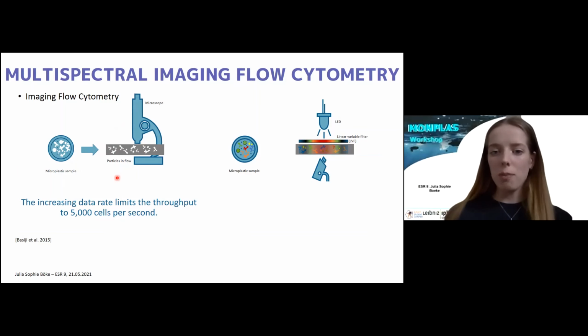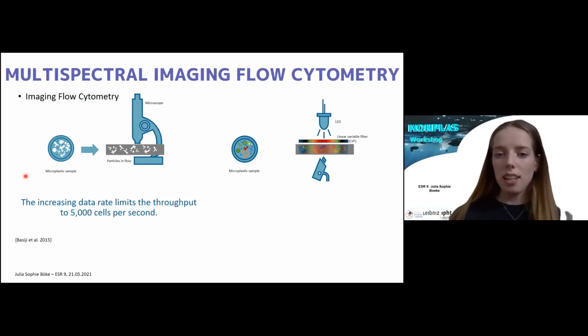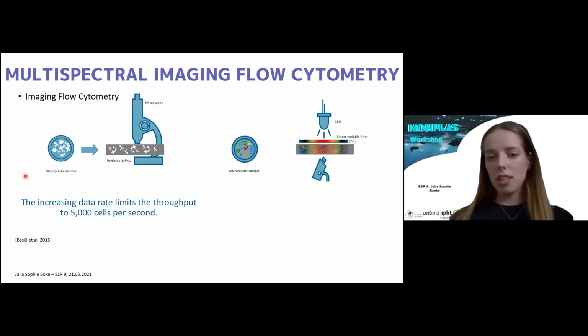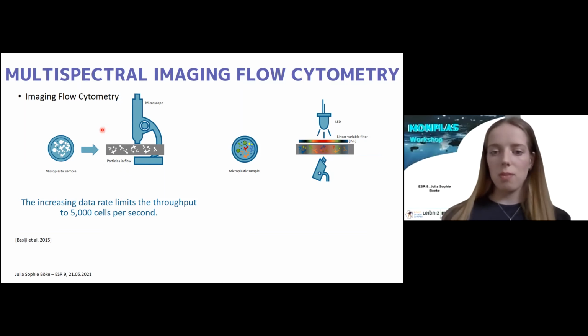So it's a very reliable technique with high throughput to analyze cells. You're able to assess the size from the scattering and partially their shape, but only partially. The main limitation is that you basically don't gain any additional morphological information or any information on the spectrum. What is then done is that you can additionally stain these particles with fluorescent dyes. There you would implement linear variable filters in front of your photomultiplier tubes as the detectors. So you could also collect their spectral characteristics and try to determine basically the material composition in terms of fluorescent signals from your samples.